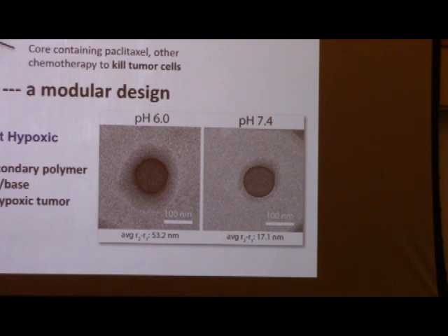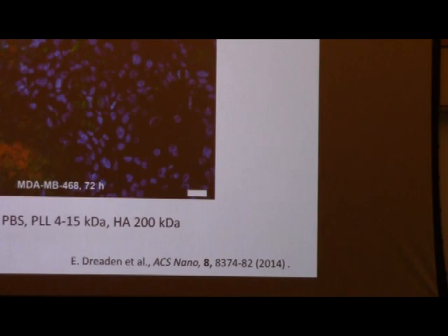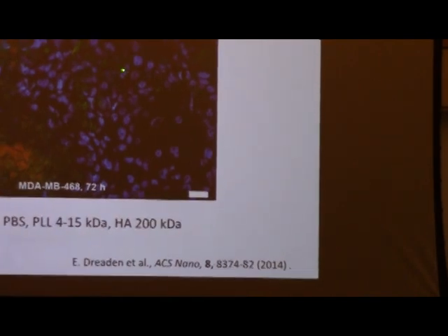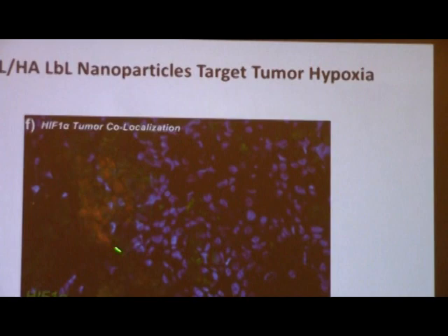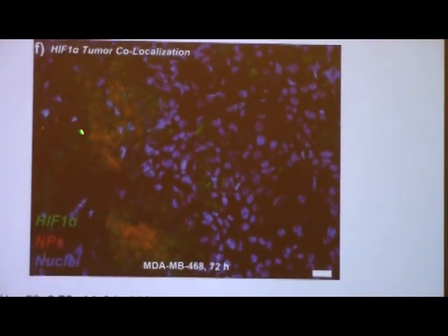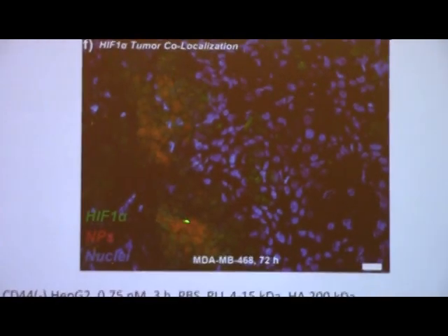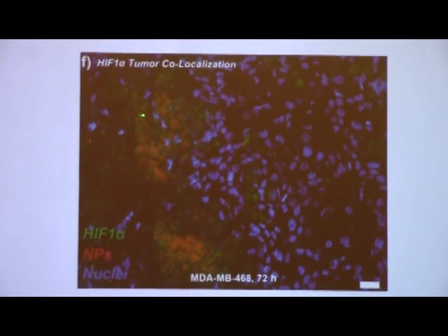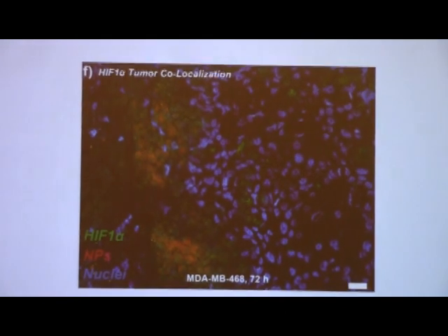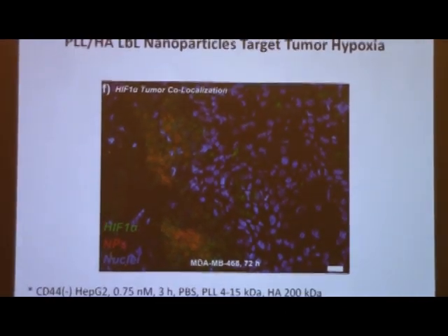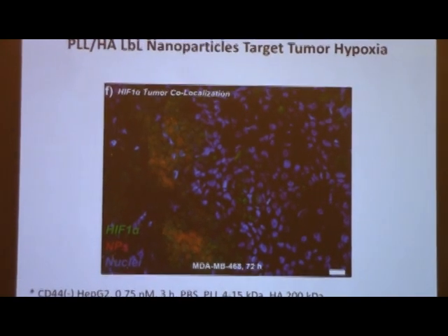So cells are now kind of interested in engaging this nanoparticle, and we see a big increase in how many of these nanoparticles are taken up by the cell when we go to the tumor compartment conditions. However, and this is actually just an image, again, I think the lighting makes it more difficult to see, but it's showing a tumor section, and the colored regions that you can just barely see are the overlap of nanoparticles with hypoxic regions of the tumor that are slightly lower in pH because they're not as good at getting oxygen to the tissue there.